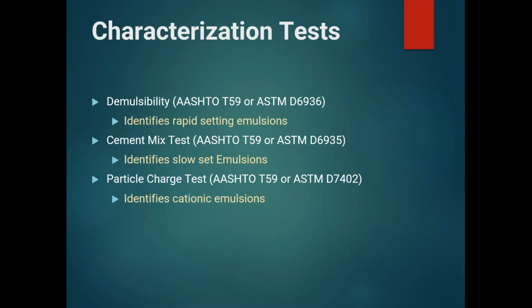A second characterization test is cement mix. This is used to identify slow set emulsions, and in this test, you basically mix cement with the emulsion, and it needs to be a slow enough emulsion with enough chemicals to mix and stay fluid when mixed with cement. And then the last one I have here is a particle charge test. And this test is measuring for a charge on the emulsion itself, and it's used to identify cationic emulsion.